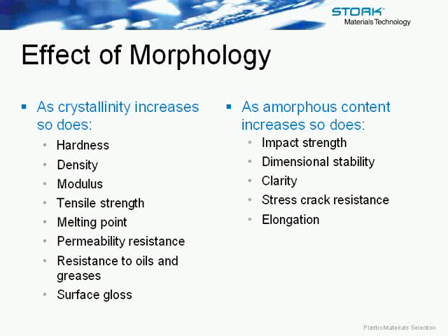Impact strength will increase, elongation will increase, along with dimensional stability. Now, these are just generalizations, of course, and are dependent on the material that you're looking at. But one important thing to note is that crystallinity can also be further controlled to some extent during the molding process. This means that when you dial in a molding process for a part in a material, once that's been optimally defined, it needs to be tightly controlled as well to ensure that the same crystallinity is maintained from part to part.